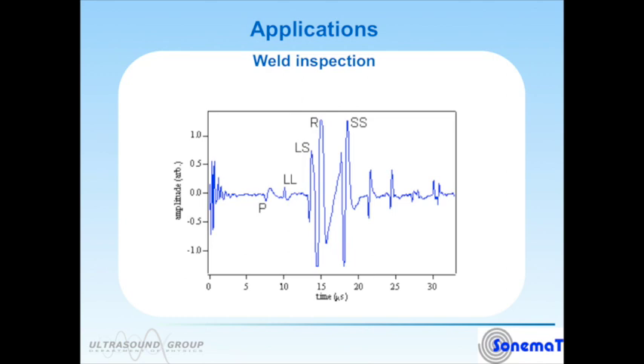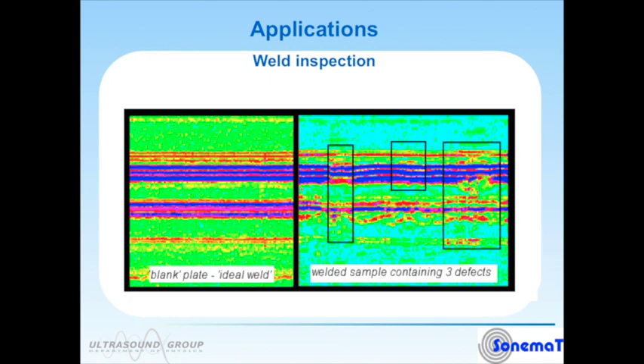An operator looking at this signal might have good reason to be worried about how on earth they were going to interpret the signal. Well, actually the key here is to take that data, turn the signal amplitude into a colour-coded map, and plot it side by side as this system is scanned along the weld. On the left you can see a blank plate representing an ideal weld, and we're able to identify what each of those coloured bars equates to there. It's a particular wave arrival. And the areas highlighted in black here, well, they arise because there are deliberate defects placed in the weld.